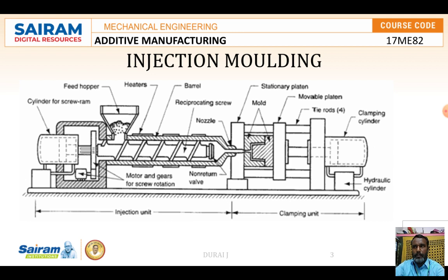Furthermore, proper flow of the molten material to the interior regions of the mold is achieved by preheating the mold to an appropriate temperature. Usually the temperature is slightly lower than the softening temperature of the plastic material undergoing molding.